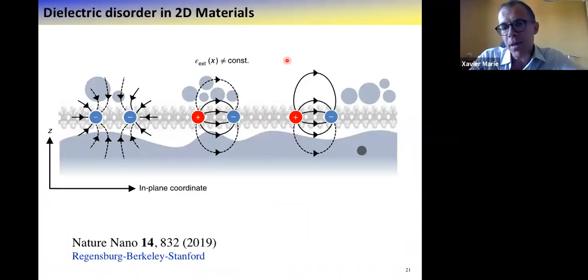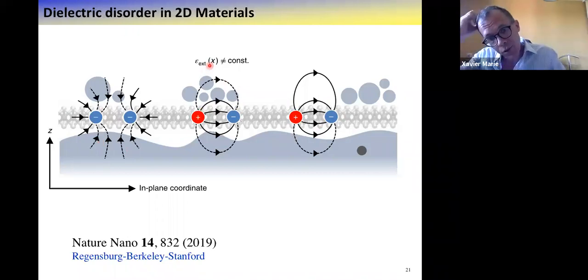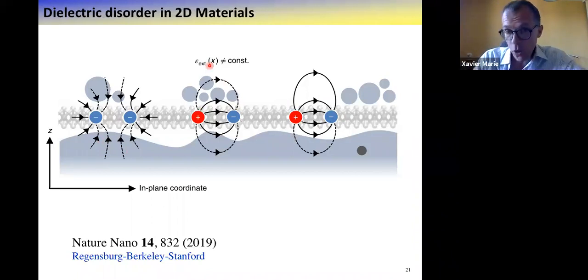So in fact, all this story can be very well summarized, from my point of view, from a picture I took from this paper from Regensburg, Berkeley, Stanford, who summarized the importance of the dielectric disorder. So here you have a simplified picture of your exciton, another one. And it's clear that if you have a rough surface, if you have defects on the surface, if you have adsorbates on top of your 2D material, each exciton will experience a different dielectric environment, and you have this strong effect of the dielectric disorder. So the key point is to control this dielectric environment. HBN encapsulation is clearly a very good way to do this.